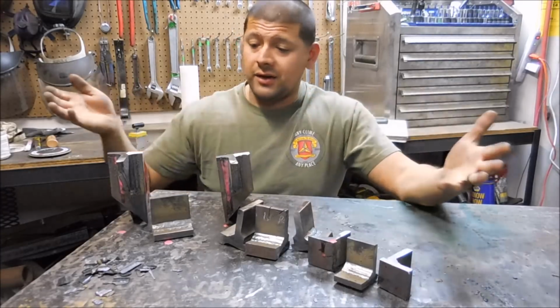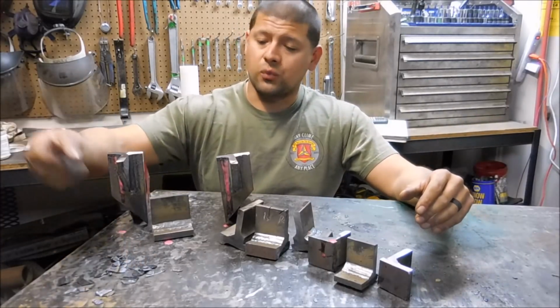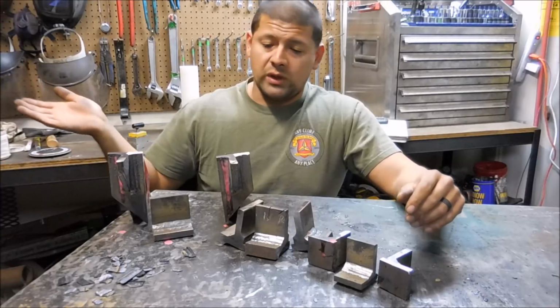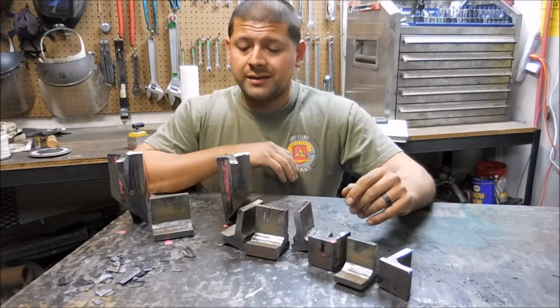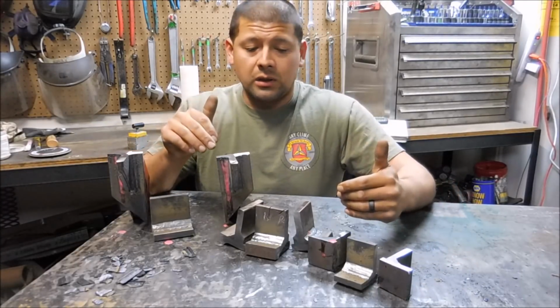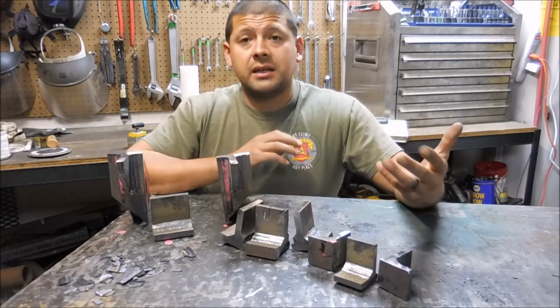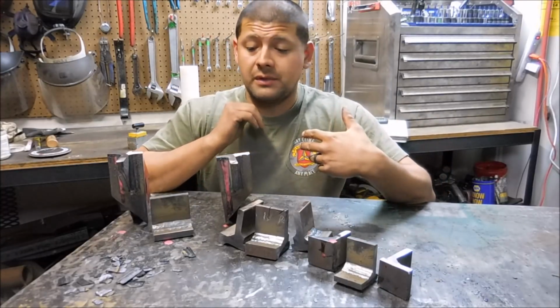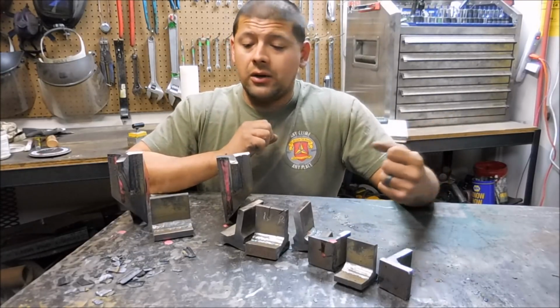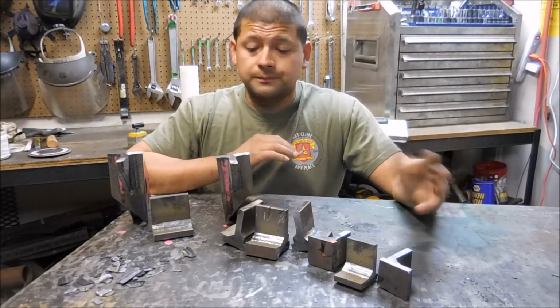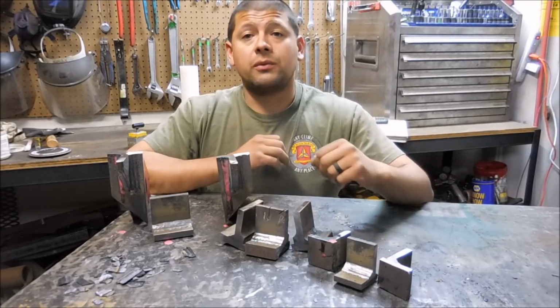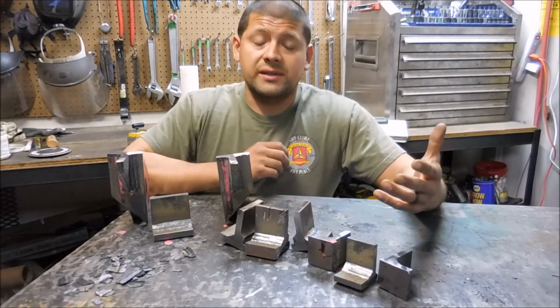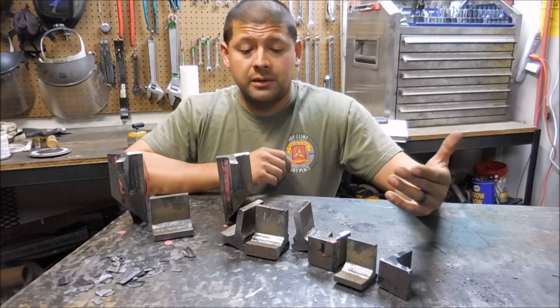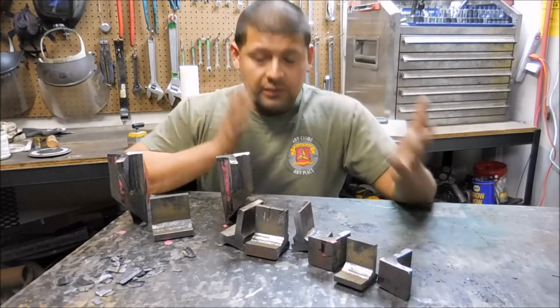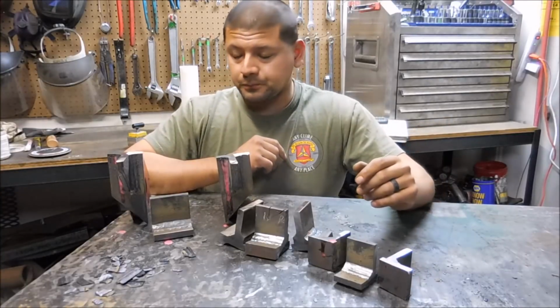Alright guys, there you have it. We welded directly over slag, we cut and etched the 3 coupons, and took a look inside the weld, and surprisingly I didn't find any slag entrapment or any major defects for that matter. I still wouldn't recommend you welding directly over slag. I don't think it's a good weld habit. I think you should clean your welds after every pass.